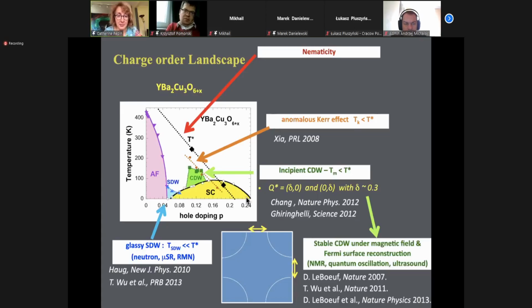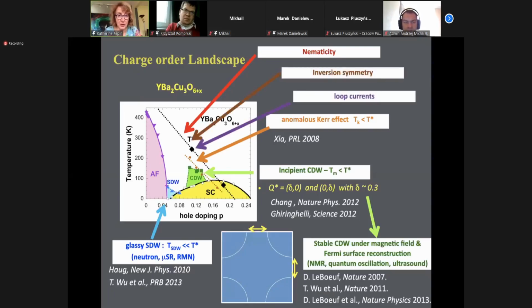At T star, in terms of discrete phase transitions, nematicity has been observed, loop currents, and inversion symmetry breaking by torque experiments. So it sounds like we have a much more complex phase diagram, with some parasitic orders. Something typical of these compounds is that you have a lot of degeneracies: you have antiferromagnetism, you have charge modulation, and you have some kind of concomitant discrete phase transition, which can appear at higher temperature and could also give a QCP under the dome, if we think of it.